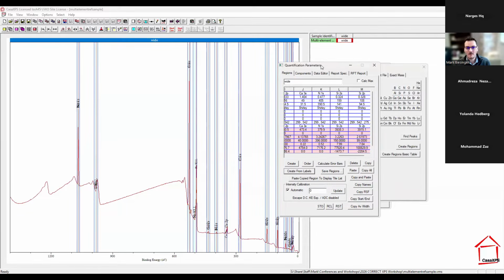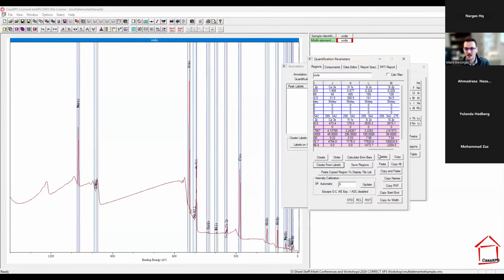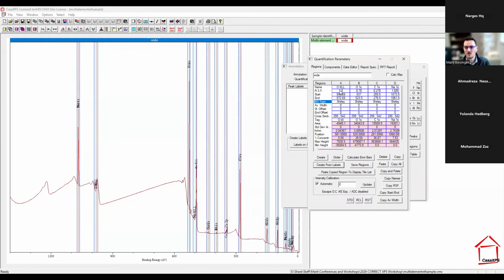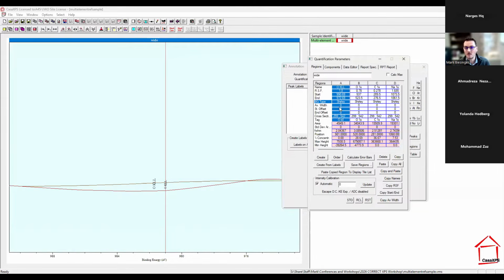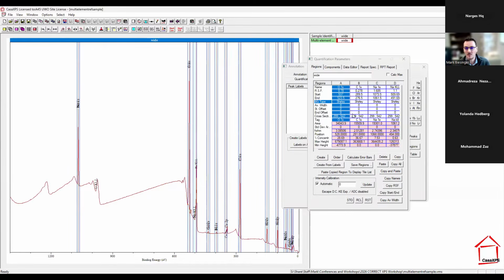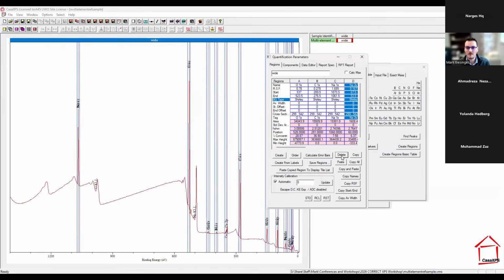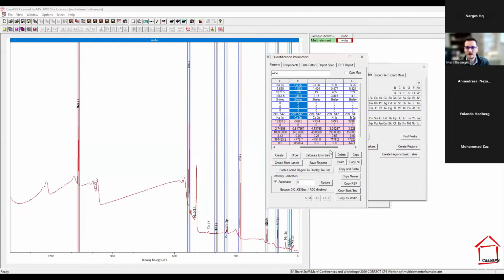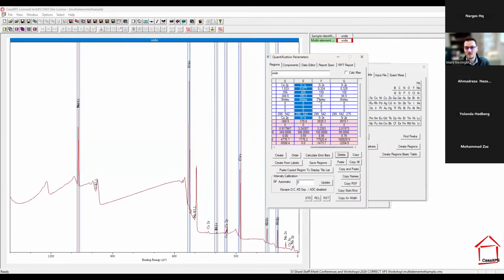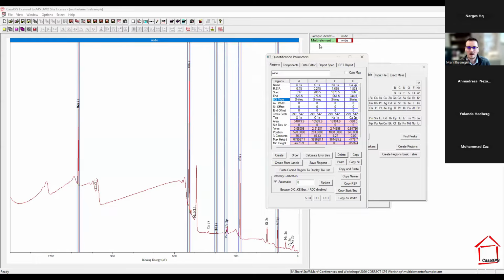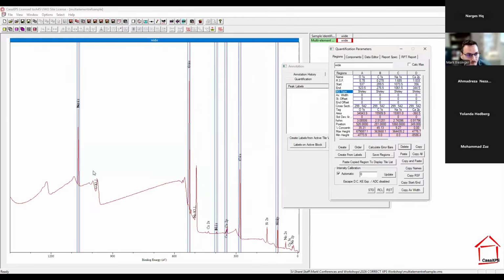Now, obviously, we've got more peaks than we should have because we've got two peaks for quantifying for oxygen. We only want one, so we're going to use the main peak, the main 1s peak, and the rest we're going to delete. I'm going to delete the sodium Auger peak, the 2s, the 2p, the calcium 2s. We're going to remove the calcium 3s, silicon 2s, and then we've got what peaks are remaining that should be used for quantification.